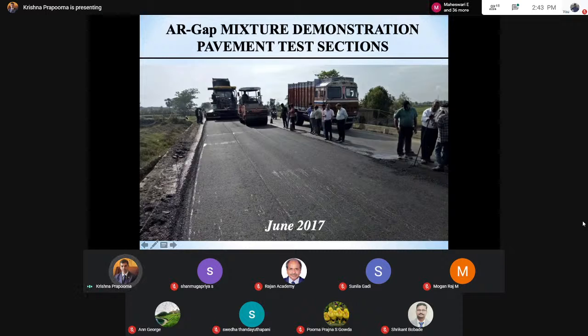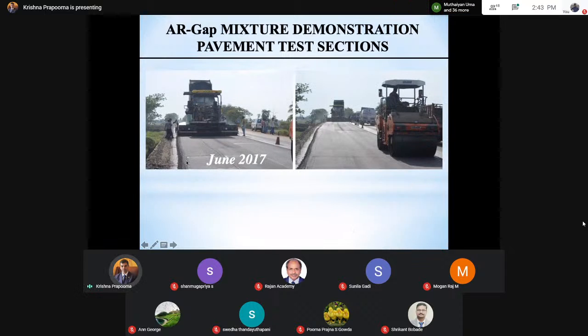Don't use it. So we told the engineers, you can see the engineering chief and the contractors, all of them here, and we were actually monitoring ourselves. The quality control was being done by us. So we said, please don't use vibratory roller. They were actually very furious with me, but I said, no, you cannot use it, because it's a very thin section. They've been used to using vibratory roller and pneumatic tire. I said, don't bring in both. Use this without vibration. That means it becomes a static steel. And you see the smoothness that was achieved at the end. So you see in June 2017, we had one paver doing the job, and we actually calculated the required number of passes.